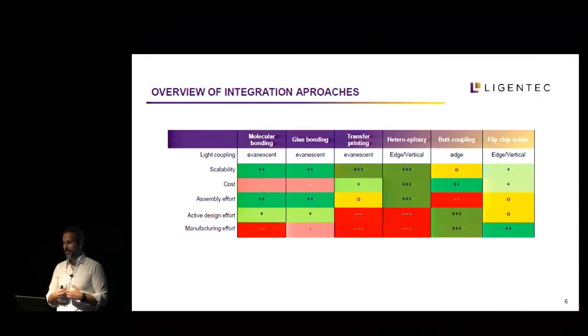This is less scalable because it's a microassembly. The cost of it, though, can be seen as low for low volumes because you just take two chips and put them together. But the assembly effort is higher because the spot sizes that you have to work with are pretty small. And as a rule of thumb, your alignment tolerance, how accurate you need to be, is 1/10 of your spot size.